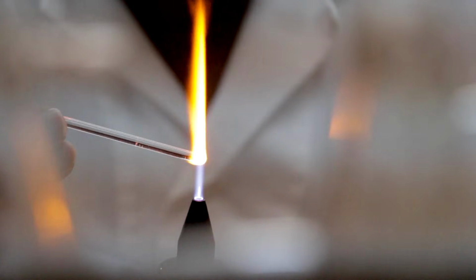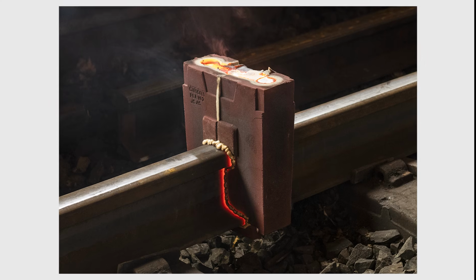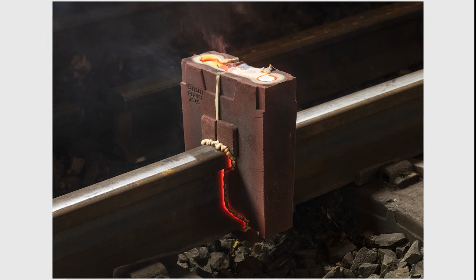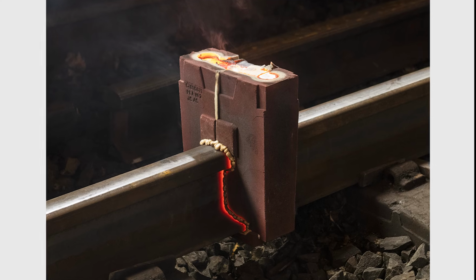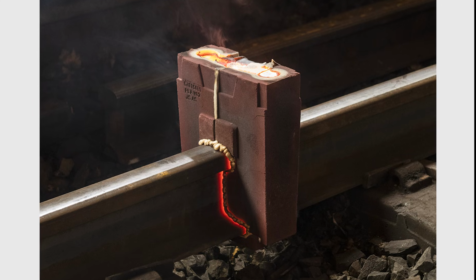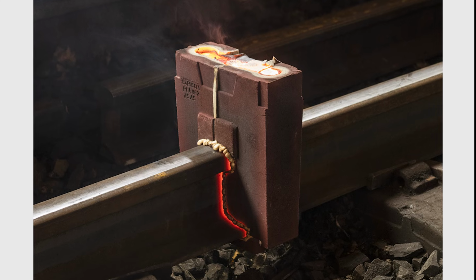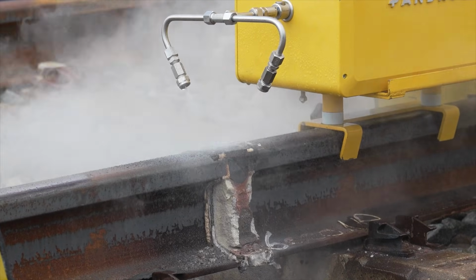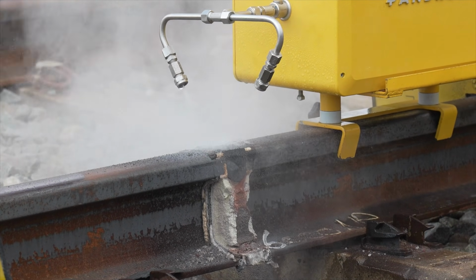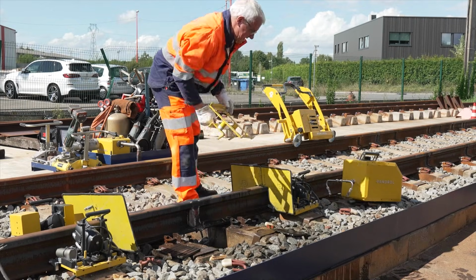Once the pour is complete, the focus shifts from chemistry to metallurgy, how that molten steel solidifies into the finished joint. The weld is normally left to cool naturally, with gradual heat loss through the mould and into the surrounding areas. In very cold conditions, insulation might be used to avoid extremely rapid cooling. However, this is changing, with products being introduced to speed up weld cooling whilst ensuring it's done under control.